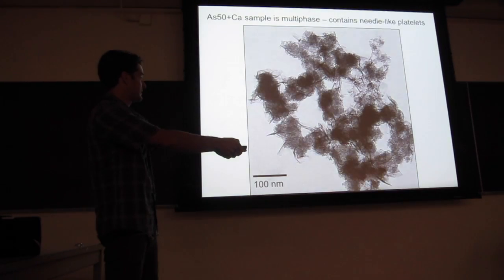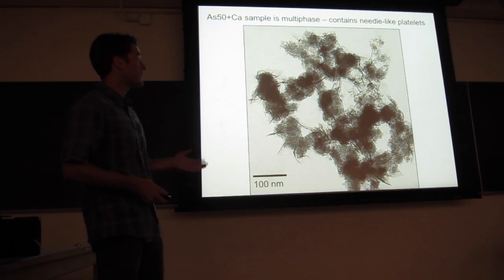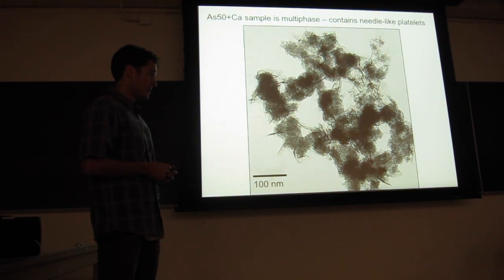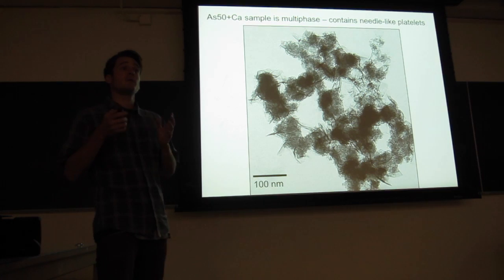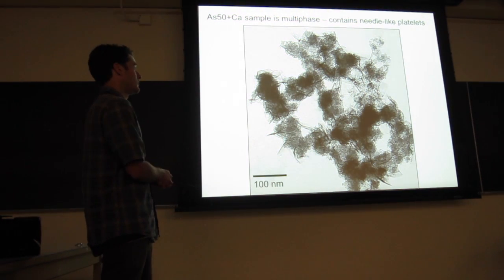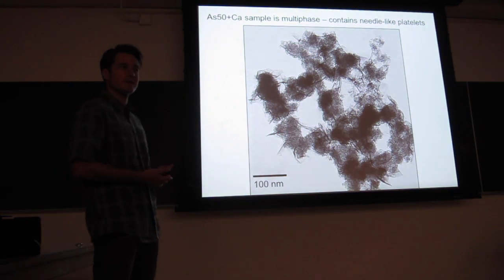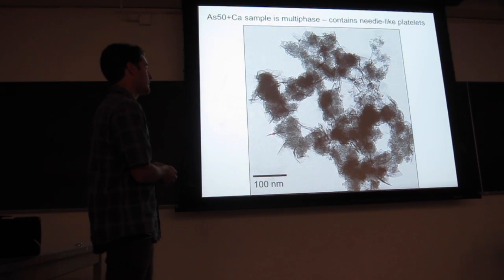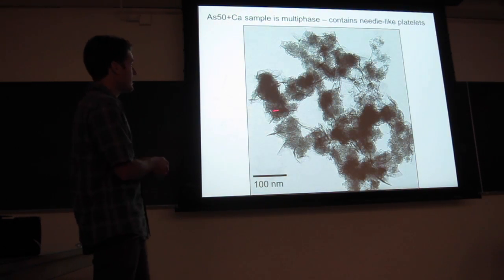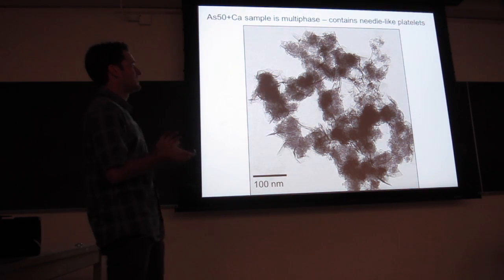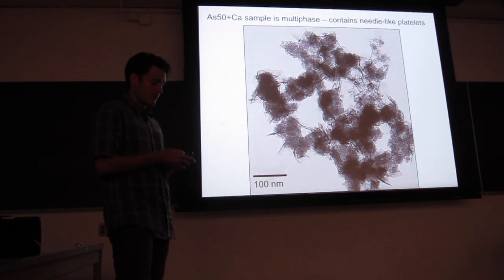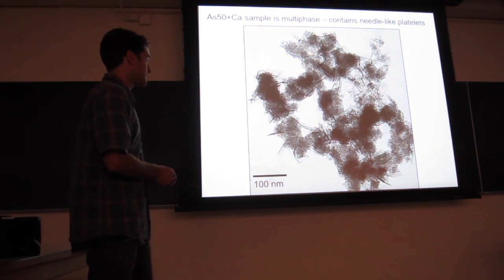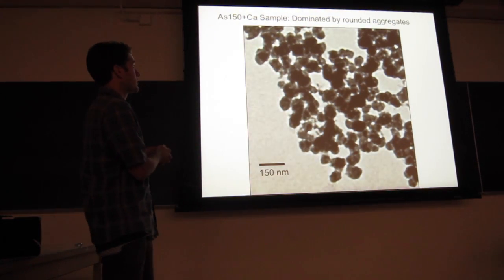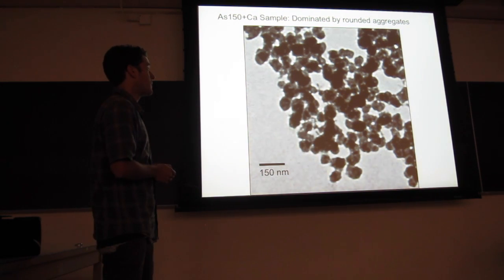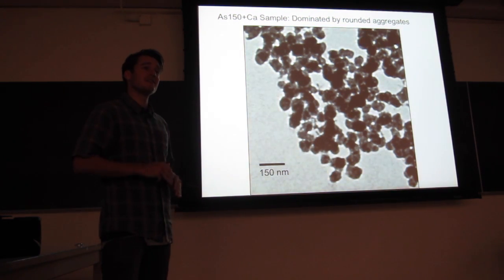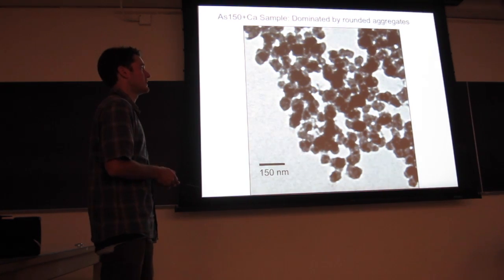And so consistent with that idea, this is a transmission electron microscope image of the AS50 plus calcium sample, where we would expect multiple phases, and we see two different morphologies. We see one morphology here, which is this needle-like platelet, which is consistent with an iron oxyhydroxide called lepidocrocite, interspersed in a bunch of aggregated spheres. And these aggregated spheres are the ones that we expect are going to be very good at removing arsenic and phosphate.